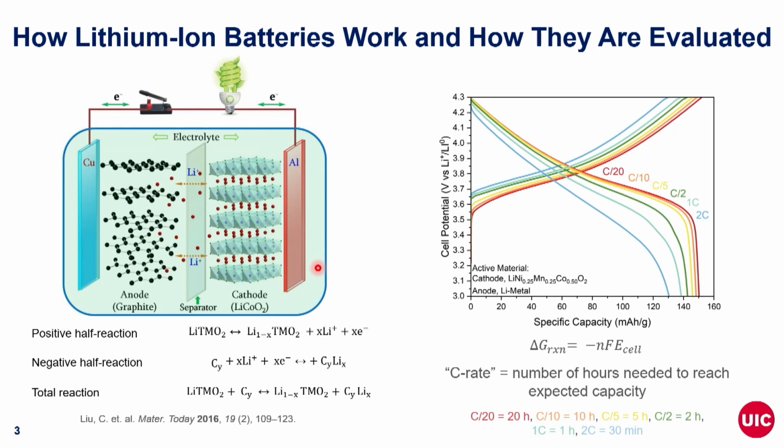So I know we don't have many battery researchers in the crowd, so I want to go through just the internal processes of the lithium-ion battery and why they are reversible. Here we can look at a schematic of the internal processes of the lithium-ion battery. Basically, the charge-discharge process and these reactions are controlled by the movement of lithium ions in this cell. So if you look at a discharge process, lithium ions are in the anode structure here. So this is just your graphite structure. Lithium ions will then diffuse or deintercalate from the graphite structure, move through this electrolyte,